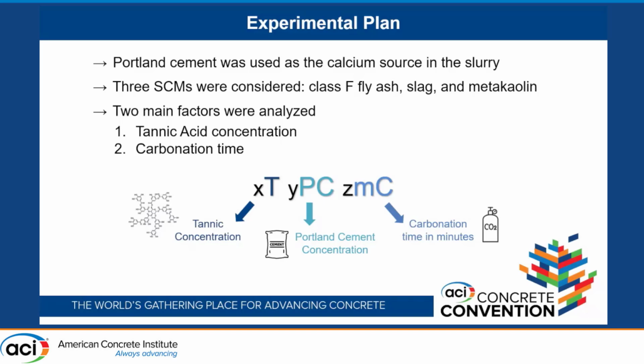So for this study, I'm just going to give you a little map so you can follow along. I'm looking into using Portland cement as the calcium source in the slurry, and then I'm using 3 SCMs to check their compatibility: class F fly ash, slag, and metakaolin. And we're looking into 2 main factors here. The first one is the tannic acid concentration, or the tannic acid presence,